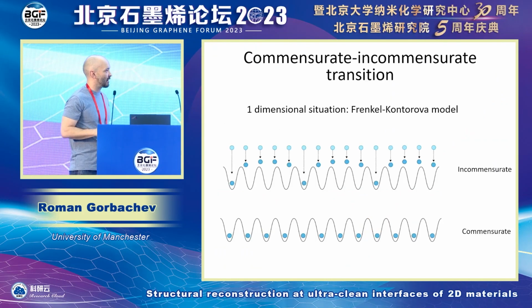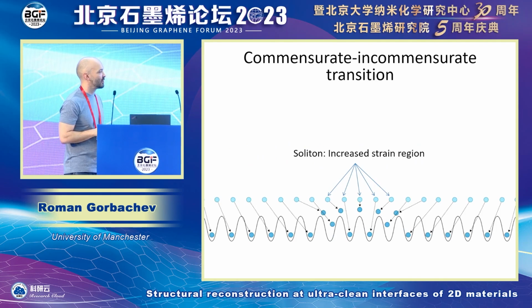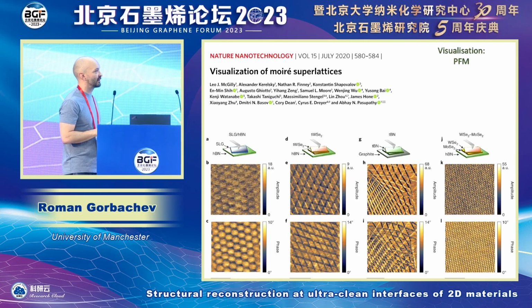locally. It's much easier to see on a one-dimensional plot. Here you can see this is the potential created by the substrate, and here we put this atomic layer of material. Instead of sitting incommensurately, they would really like to sit commensurately to decrease their adhesion energy. What they do to solve this problem is strain locally to click into the underlying lattice. The excessive strain produces the boundaries between these nice, perfectly clicked regions. In fact, you can see this if you do, for example, piezo AFM; you can see these lattices quite clearly. However, for this technique to work, your sample needs to be exposed, so you cannot encapsulate your sample with hBN, for example, and visualize the moiré pattern.